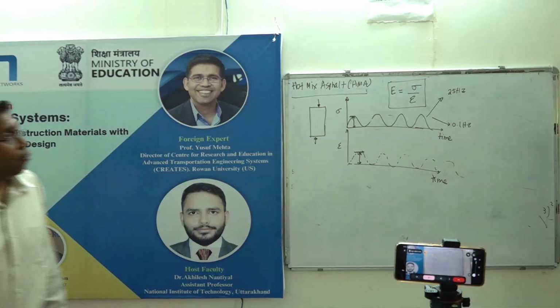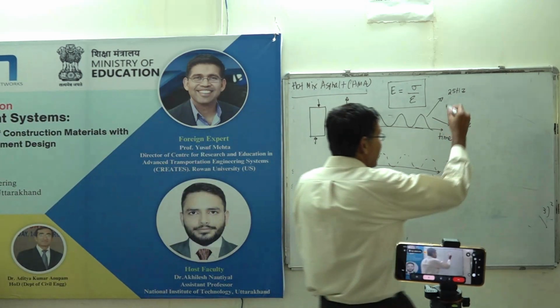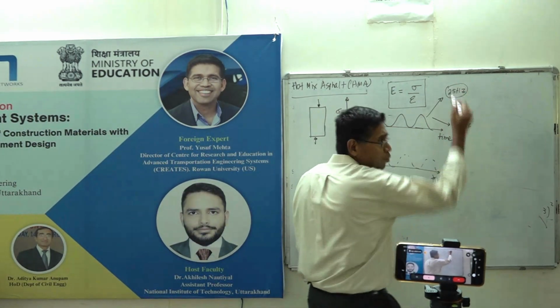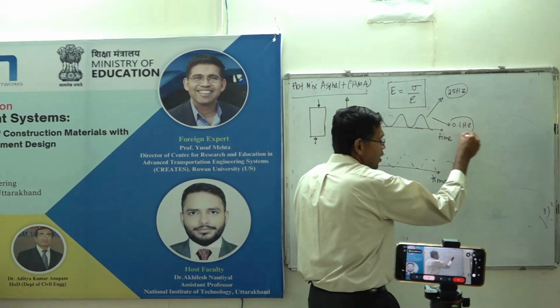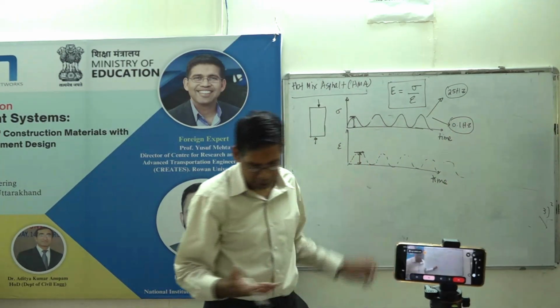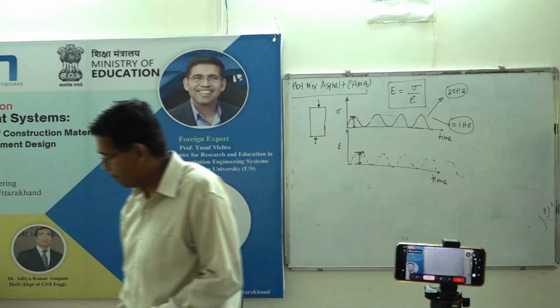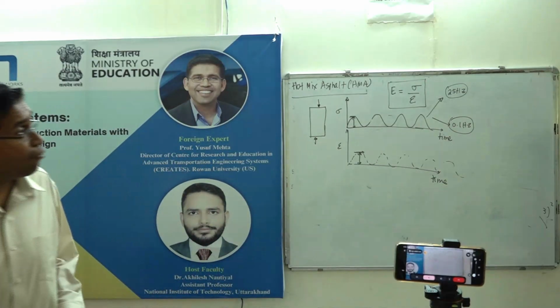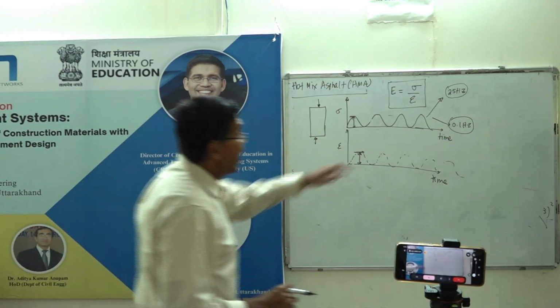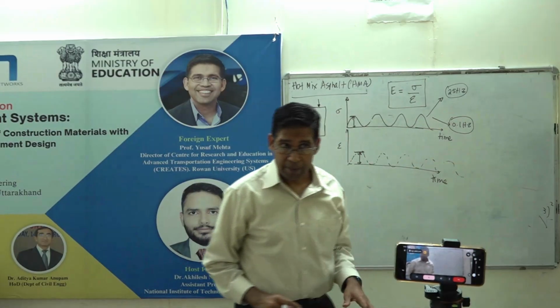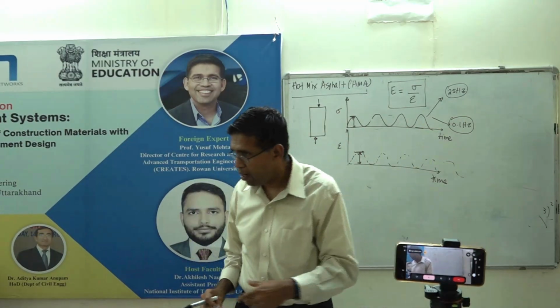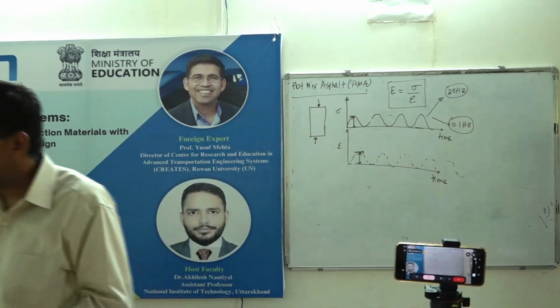Okay. Now, this, of course, is very clear. This is for heavy traffic, fast-moving traffic. This is for standing traffic. 10 seconds, give or take, right? 0.1 hertz is 10 seconds. Right? So you have to do this test at every temperature at different frequencies. Everybody understood that? So there's a software, you put it in the machine and you will do that.